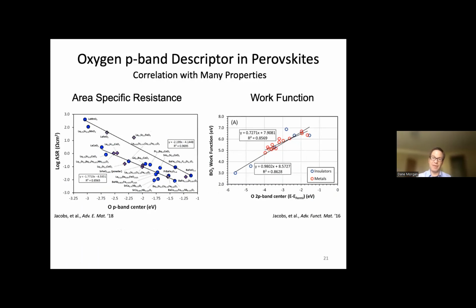So here are measures of actual area-specific resistance in a series of different perovskite materials. We plotted this as 2 lines because we think there might be 2 curves here, and I'll skip the details, but the qualitative result is that as you increase p-band center, area-specific resistance seems to decrease. So these are materials that were actually tested in a configuration for use as a fuel cell and showed that their essentially fuel cell performance, their area-specific resistance, trended in a pretty strong way with oxygen p-band.